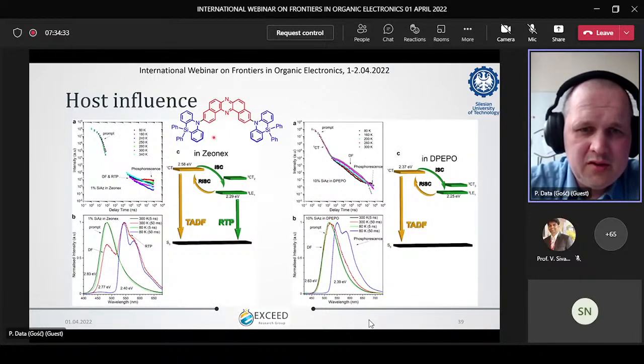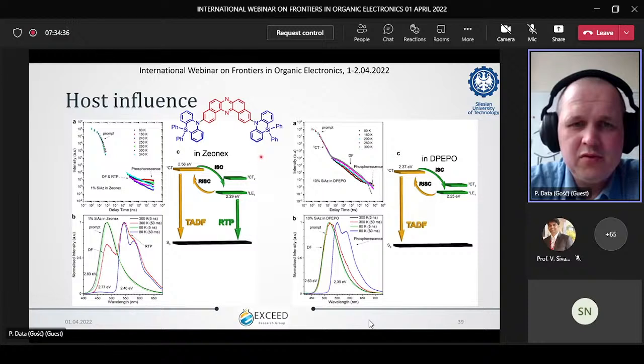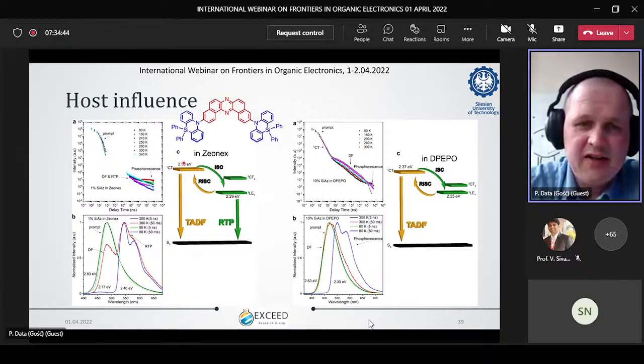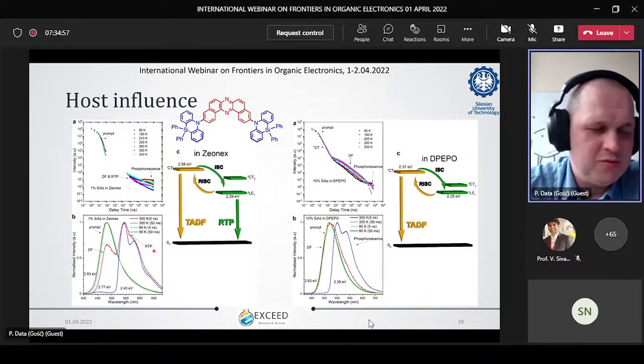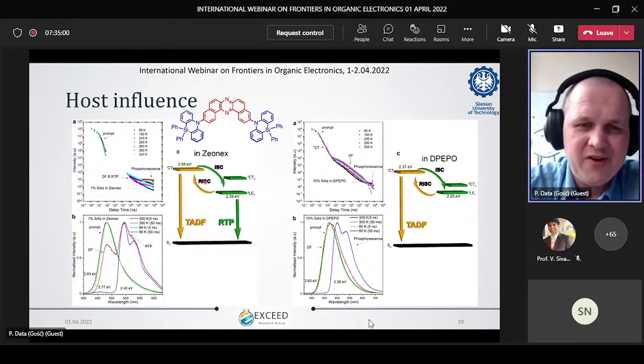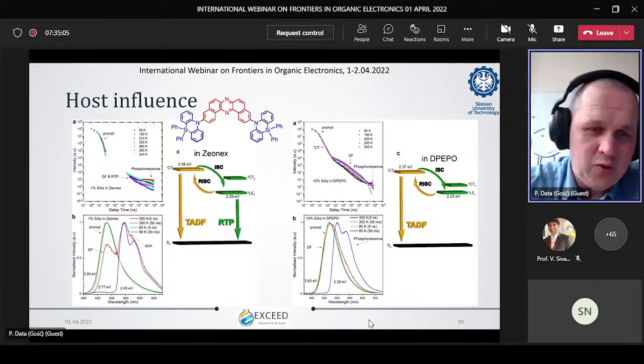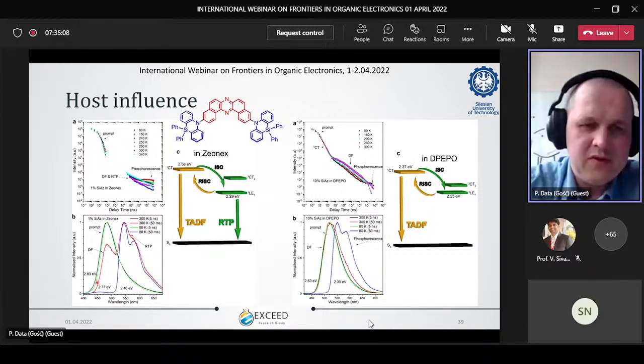So going closer, if you look closer, what happened here? In polymer Zeonex, which was solution processed, we actually had dual emission: room temperature phosphorescence and the TADF process, which fight with each other over which will be more efficient. But we had dual emission, and in the steady state as well we observe both the TADF process and the room temperature phosphorescence.